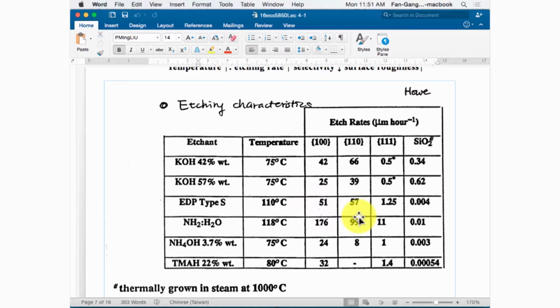Okay. So remember, the etch speed for EDP for 100 and 110 wafer is opposite to KOH etching, because we will discuss about the corner compensation design. Because we will design 2 totally different types of corner compensation for these 2 etchants.